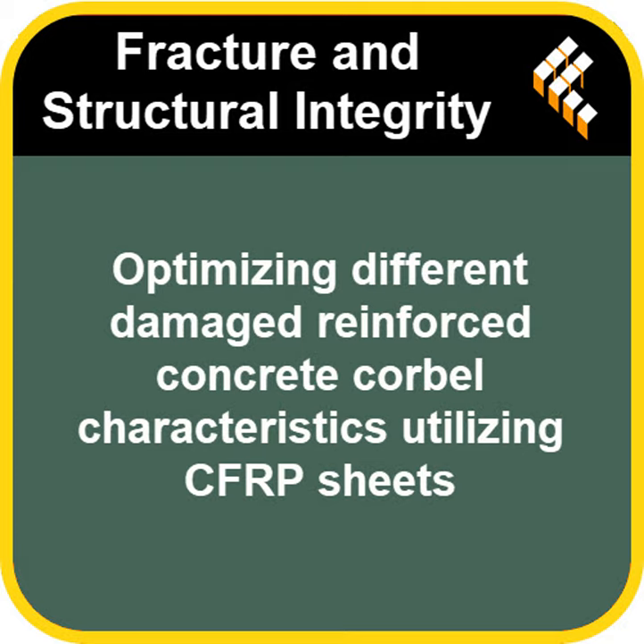Yeah. The CFRP material itself is brittle. It won't stretch much. Right. But when it's bonded effectively to the concrete, it changes the system's behavior. It acts like a confining wrap or reinforcement. Okay. How does that help ductility? Well, as the concrete starts to crack or crush internally, or even as the internal steel reinforcement starts to yield, the external CFRP layer holds everything together. It prevents sudden, catastrophic failure modes like explosive splitting. Ah, so it contains the damage. Exactly. It forces the failure to be more gradual. The system can deform more, absorb more energy before it ultimately loses its load-carrying capacity. Even after the peak load is reached, the load decreases more slowly rather than dropping off suddenly. So it gives warning. A less brittle failure for the entire corbel. Precisely.